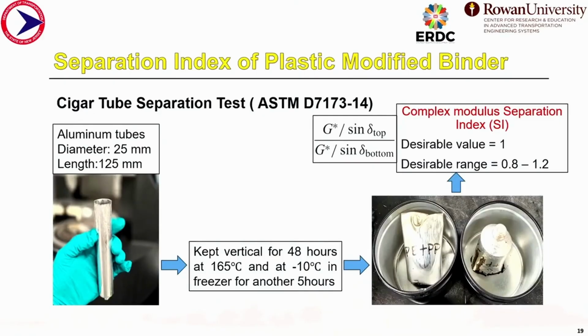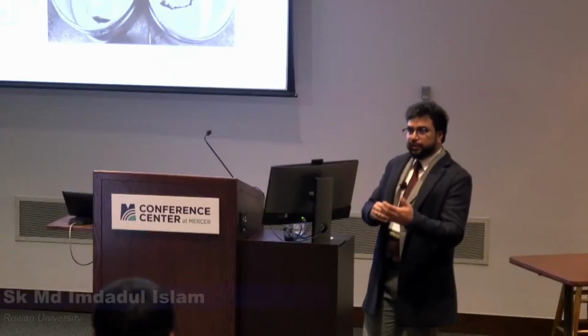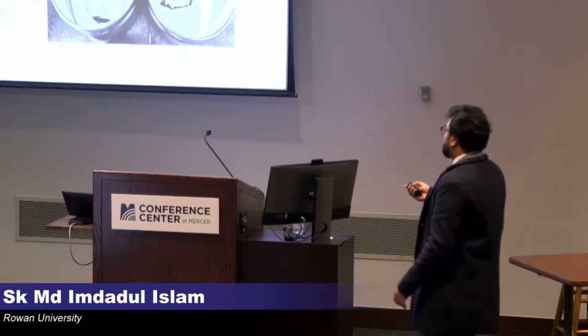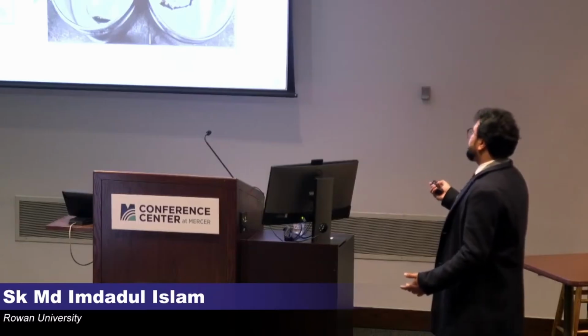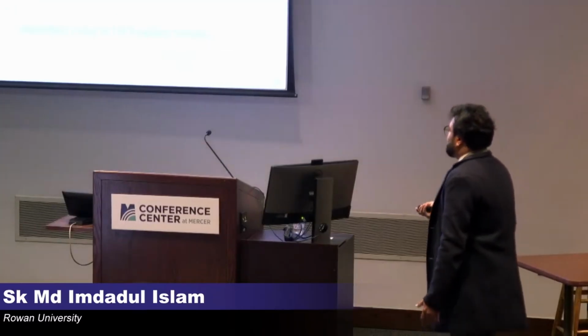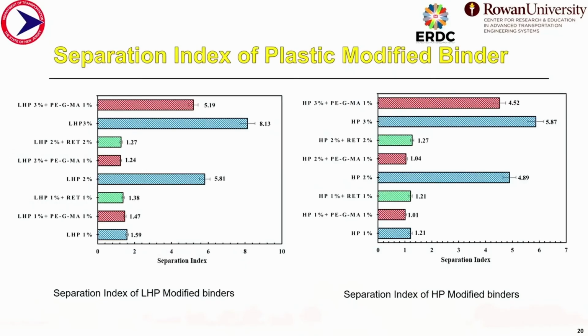So the ratio of G star over sine delta is called the complex modulus separation index, and the desirable value should be 1 if the modified asphalt binder is homogeneous. That means the G star over sine delta ratio from the top and the bottom should be equal if it's a homogeneous mixture. With a desirable variation of 20%, we can get from 0.8 to 1.2. If we look at the results that we get from the separation index test, we can see these are the SI, or separation index, values for different types of plastics. On the left side, we can see the separation index values for LHP plastic with the stabilizers, and here we can see the HP plastic with different stabilizers.